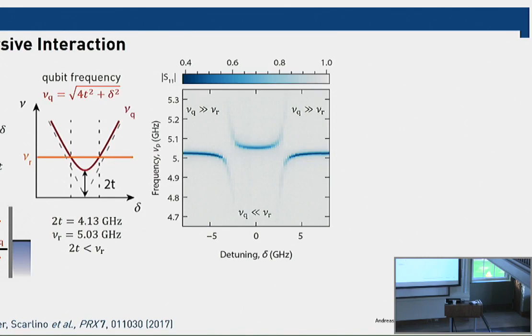So here's then a measurement of the reflection spectrum of the high impedance resonator versus the detuning between the left and the right quantum dot. And you see that as the quantum dot approaches from above, the resonator frequency gets pushed downwards. Here in the middle, you would expect some anti-crossing and the vacuum Rabi mode splitting, as the double quantum dot goes through its minimum transition frequency and then comes back up.